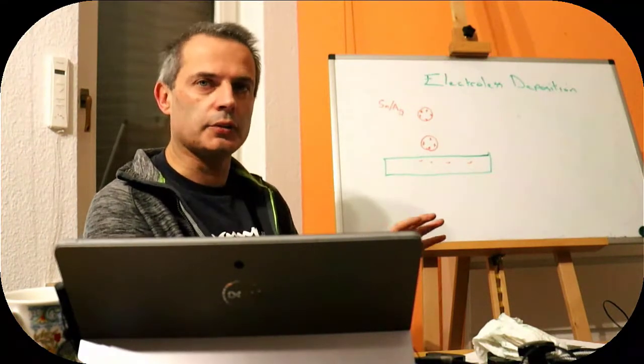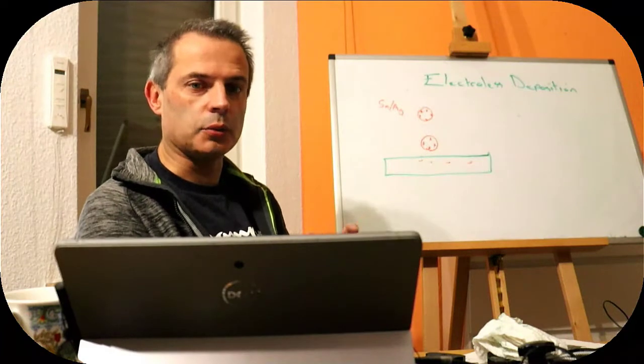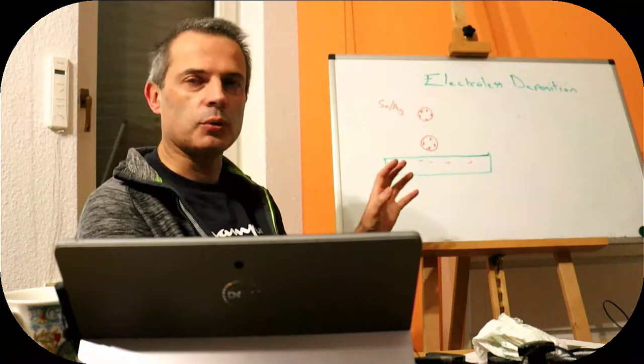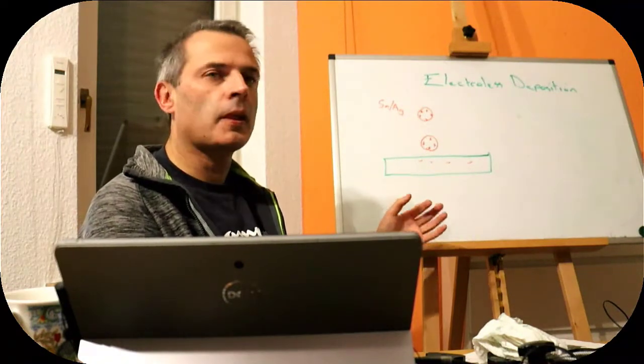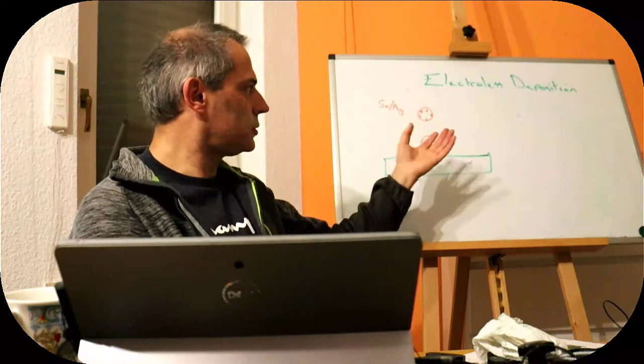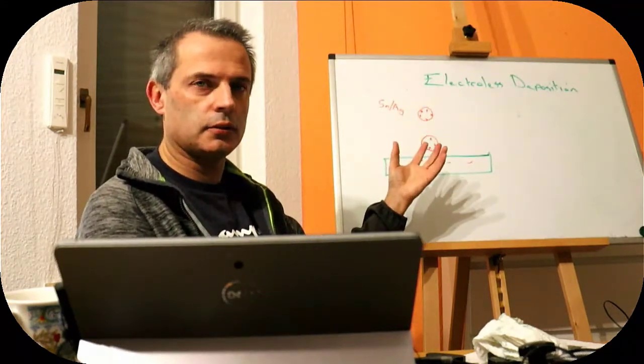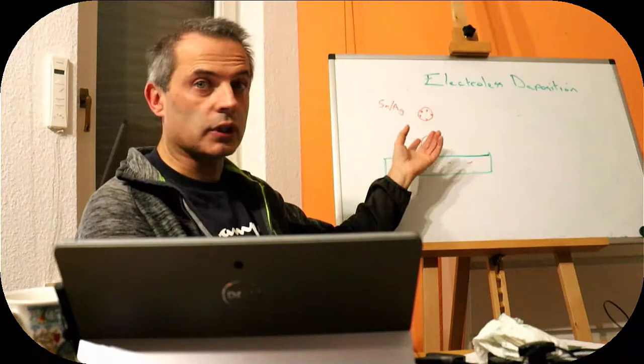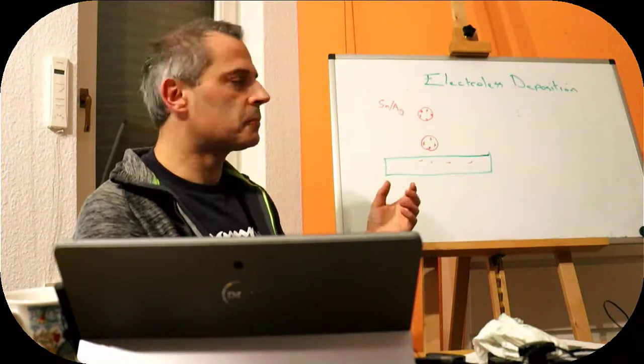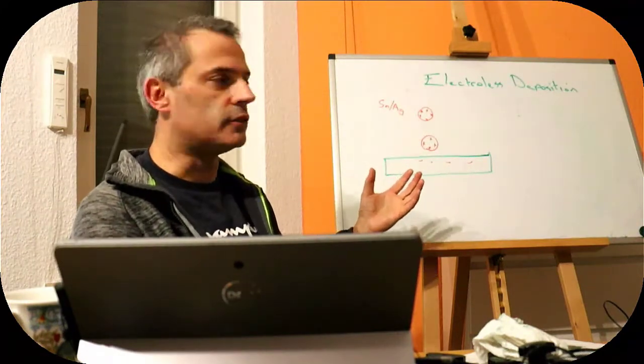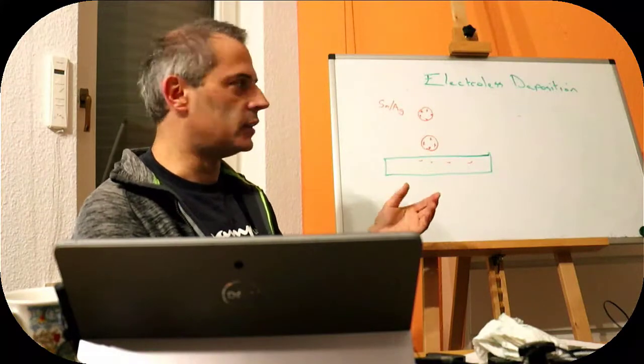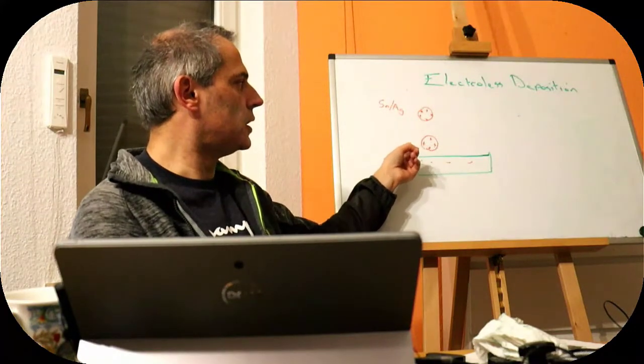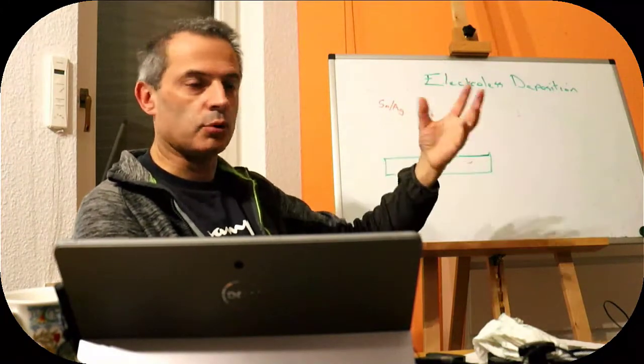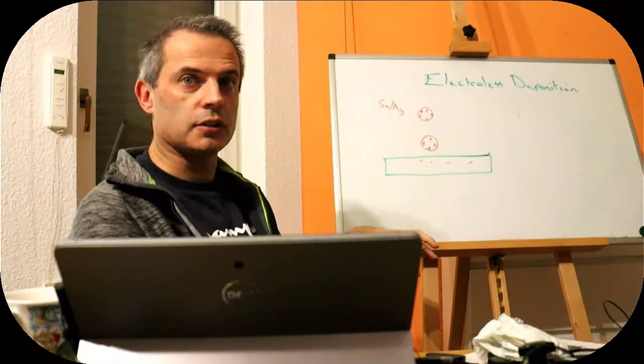In solution, that's the best we can do, unless we do some tricks, but that's what we're going to get to typically. Then we can take this out, and this is actually attached, but if we wipe it, this will come off. So we don't want that to happen. And the easy way to fix that is to allow it to dry. If we allow it to dry, the water in this gap will evaporate and the particle will touch the surface.